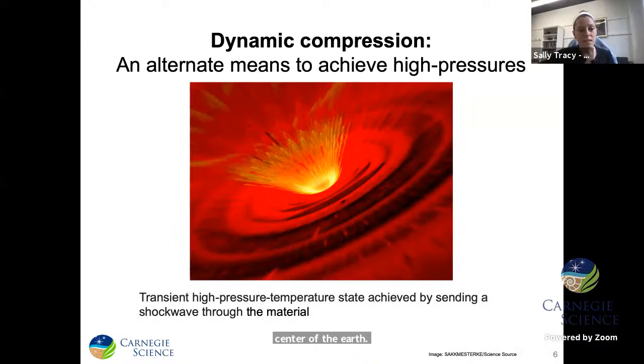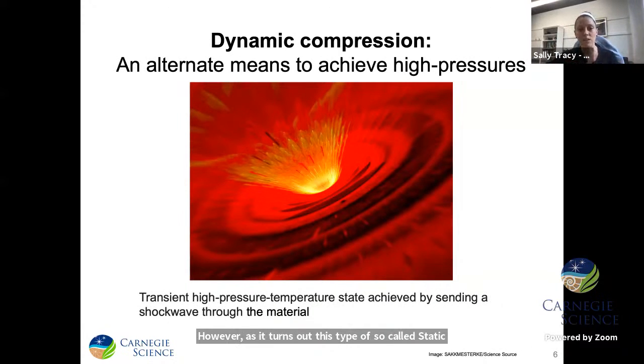However, as it turns out, this type of so-called static compression isn't the only way to generate high pressures in the laboratory. And much of my recent research has instead focused on a different technique known as dynamic compression, which is exactly what it sounds like. In these experiments, we generate a transient high pressure state in a material, which we achieve by sending a shock wave or a rapid compression wave through our sample, either by using an impact launcher device or alternatively with high intensity pulsed lasers.